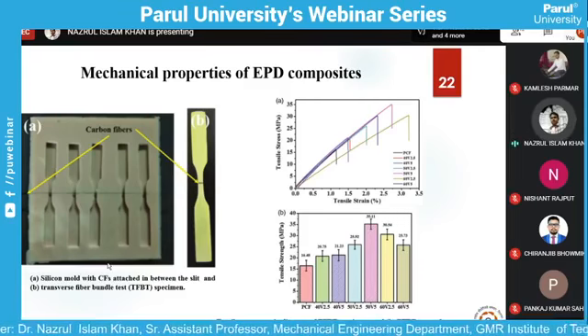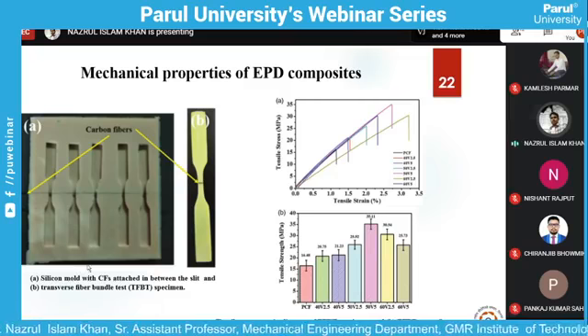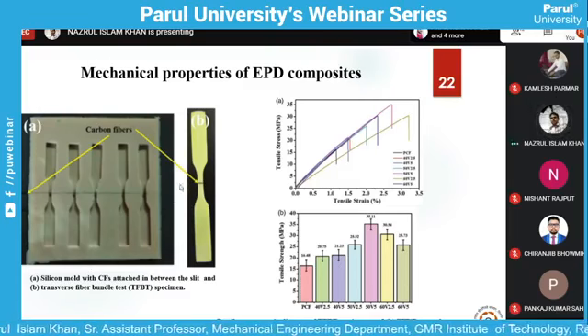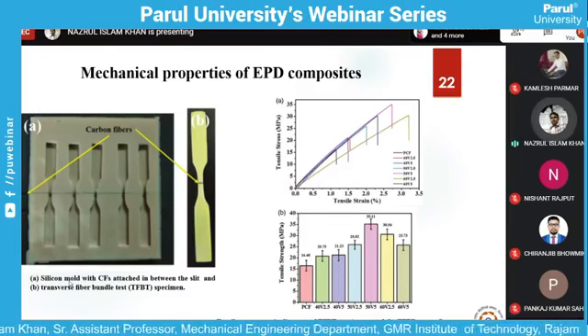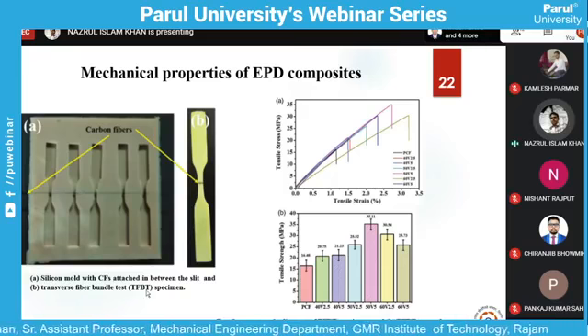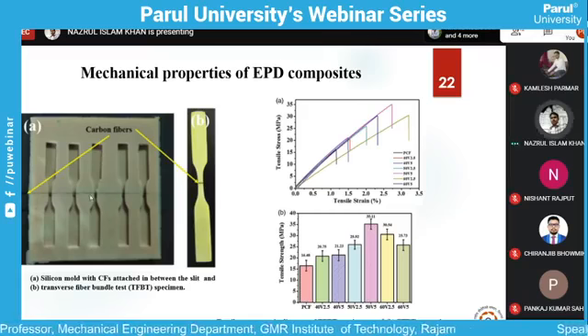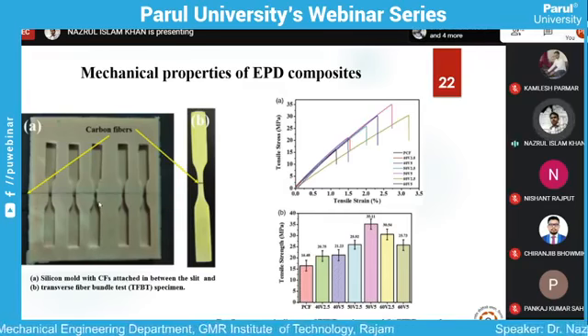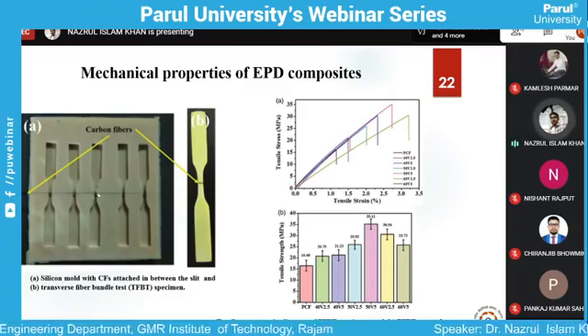And what type of composite, we wanted to see what is the bonding between fiber and the matrix. For that we prepared a transverse fiber bundle test, TFBT test, where the fiber was kept in transverse direction and the matrix was poured along the silicon rubber mold, and once it flows over the cavity, this TFBT test applies a transverse load on the surface of the fiber.